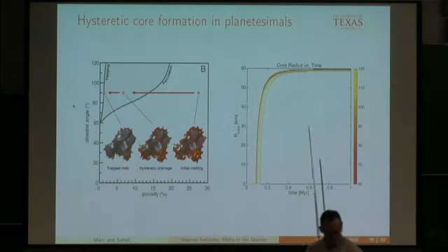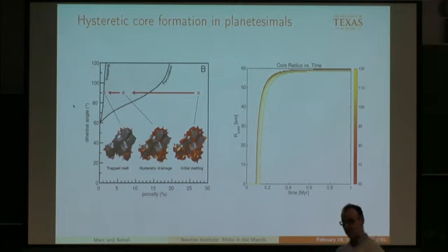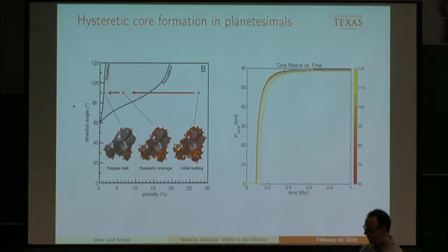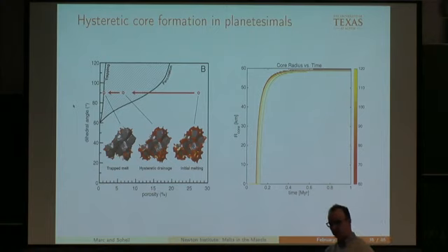I have this following idea that in these systems, if you have high porosity, I think the dihedral angle just doesn't matter at all, personally. Because if you have 30% porosity, anything will connect. Even if you had a 180 degree dihedral angle and you had a bunch of spheres at 30%, they would connect. One of the reasons that we looked at the meteorite is because we weren't sure whether it was at all realistic that you would ever reach porosities that large.